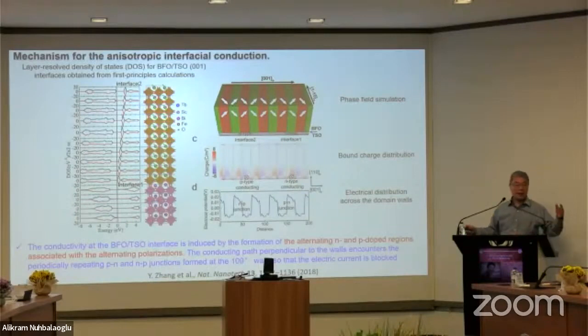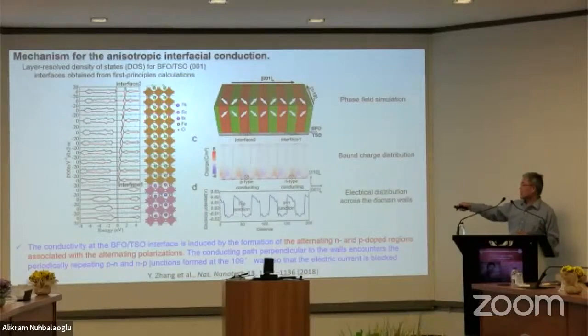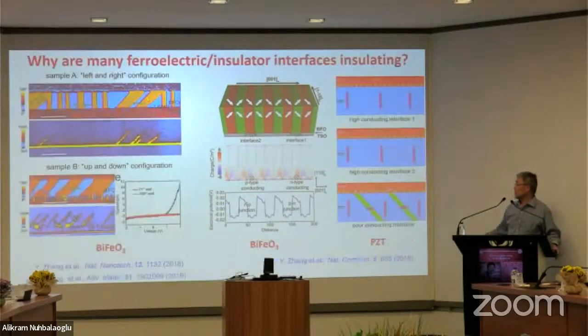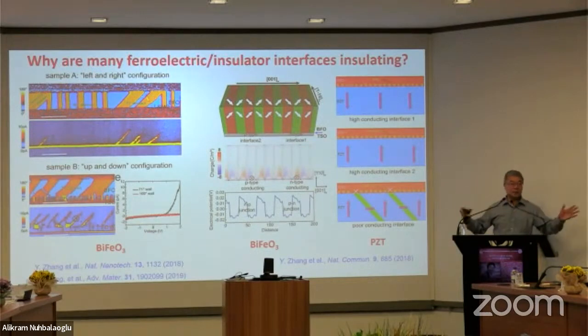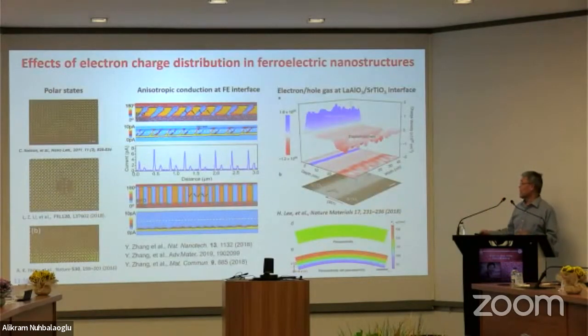This explains why when we measure the conductivity across the domain stripe it is insulating, because they're just in series connection. But when we measure along the stripe, it is all conductive. So that was very interesting to observe. This just summarizes the conductivity of two different kinds of ferroelectric interfaces. It explains why in the microscopic measurement it is insulating, but at the nanoscale it is conductive. Okay, so this addresses another question.